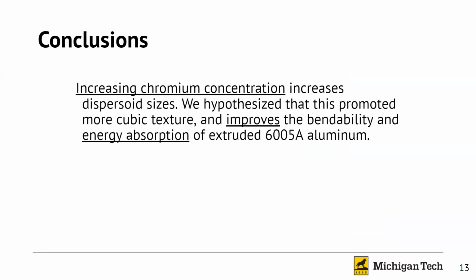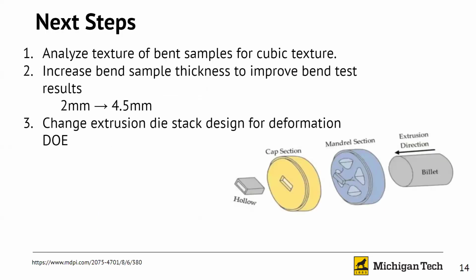In conclusion, increasing the chromium concentration increases the dispersoid size, and we hypothesized that it increased cubic texture and therefore improved the bendability and energy absorption of the 6005A aluminum. And our next steps include analyzing the texture of these bent samples, increasing the bend sample thickness so that we can get bend angle, and changing the extrusion die for deformation.